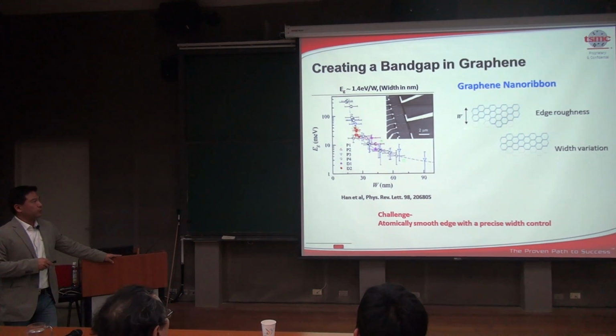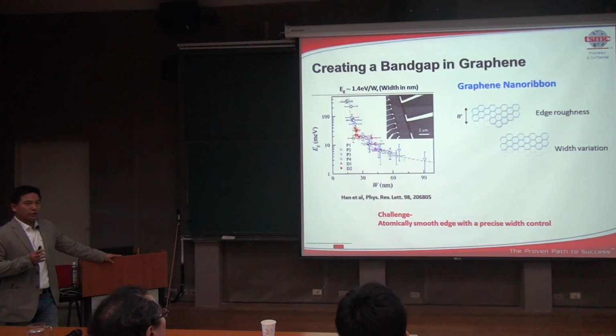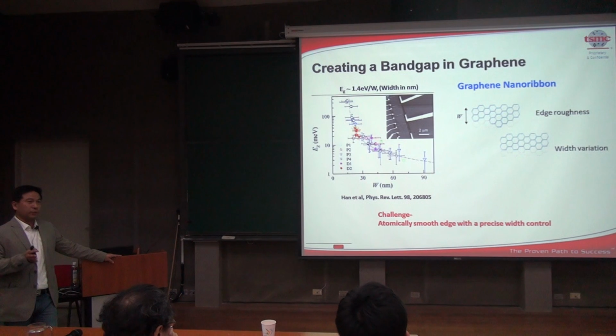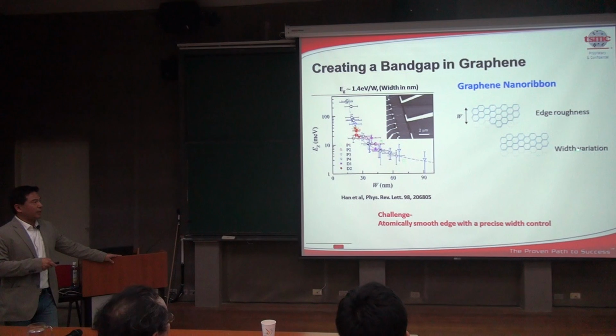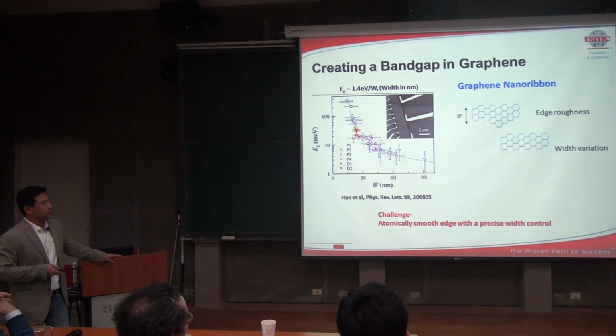One of the challenges for this to work is to control the edges, because to create a bandgap, you etch graphene into a ribbon-like structure. So you will have some kind of uncontrollability due to the process that causes the edge roughness, as you see here, or the width variation. Now the width variation will be even more dramatic in changing the material from a semiconductor to a metal. So just by changing one line of atoms, you can change this property from metal to semiconductor.